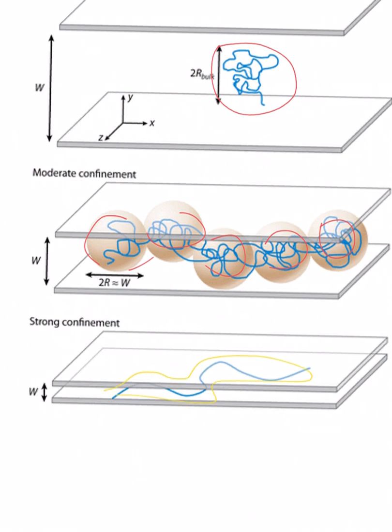And we also then produce a very intimate association between the polymer chain and the plates that are squeezing in on it. And so what this does is it gives us a sharing of properties that's very, very intimate, very well mixed. Okay? And this is how Toyota makes timing belts using clay nanoparticle particulates and nylon. And they mix those together and they crank out these timing belts that are based on these nanocomposite technologies. All right, this is part of the interest and excitement about nanocomposites, is being able to squeeze things together and get very good load sharing between them because you've made them very, very well mixed in this structure. But you start with R sub g and you squish it, and then try to get this very close association.